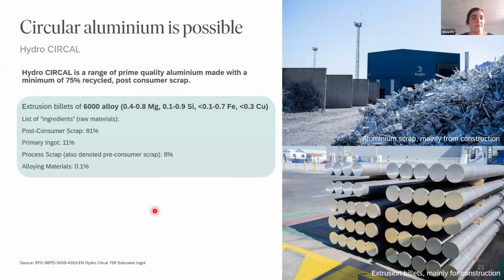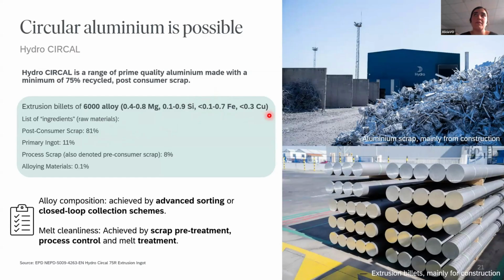Currently, there is some circular aluminium that we are producing. This is what I mentioned earlier, branded as Circal. Hydro has several plants producing this with at least 75% post-consumer scrap. Here we have the average composition of this alloy from the environmental product declaration. This is mainly used for construction, and the source of the scrap is also mainly coming from construction. Circularity is being achieved in this case by securing the cleanliness of the melt, by the pretreatment of the scrap that contains coating contamination, and also by advanced sorting.